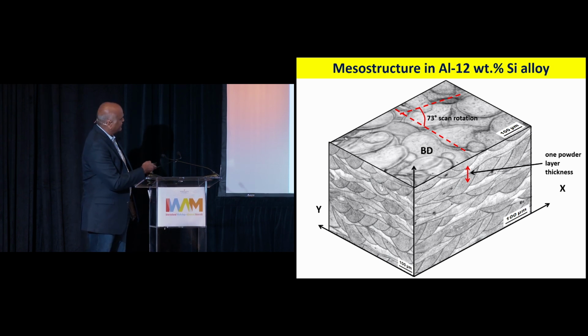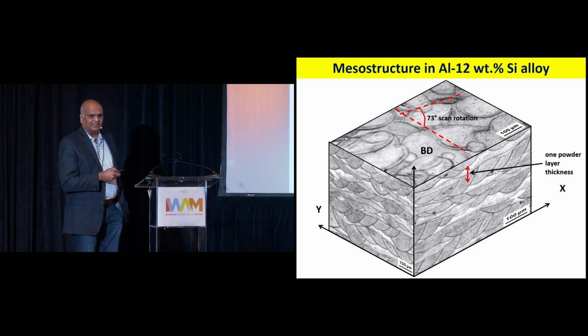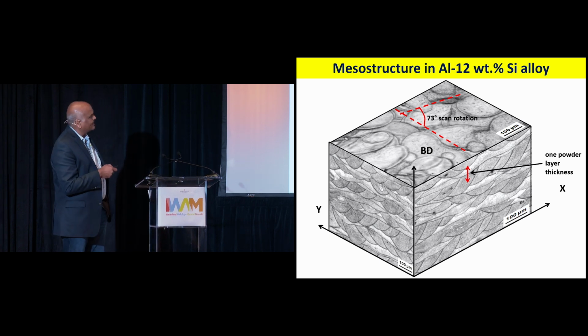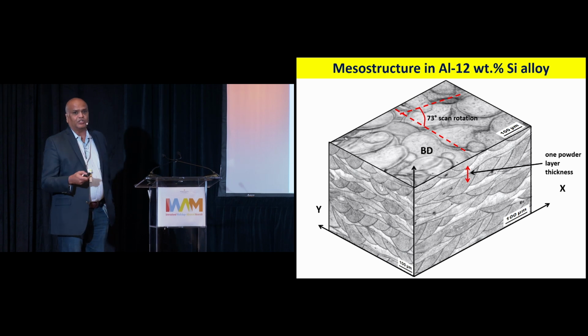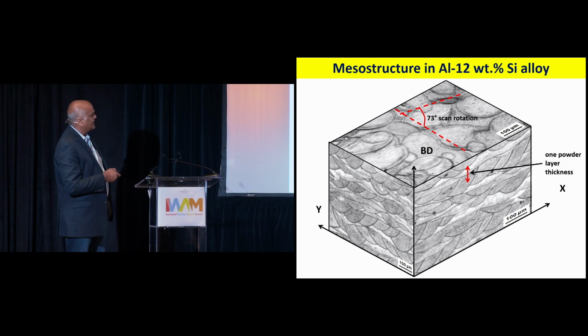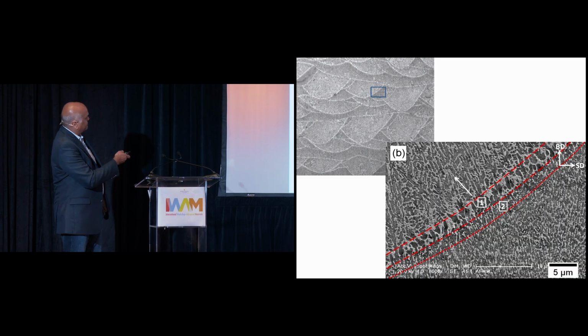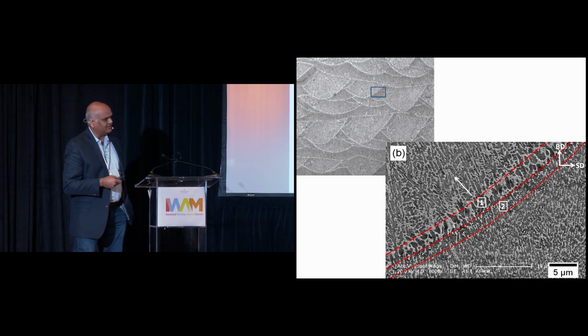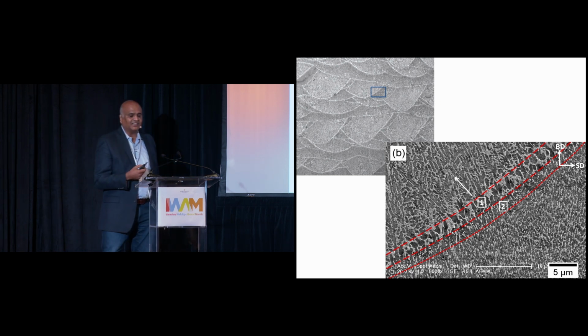And so each of these is one line, cross-section of one line, and you can see them overlapping, and then you rotate 73 degrees between successive layers, and you get these things. So what happens is that in this particular material, because silicon's solid solubility is very low, silicon essentially decorates these hatch boundaries, right? So for example, you can see these boundaries. If you magnify it, silicon is rich, they become silicon rich.